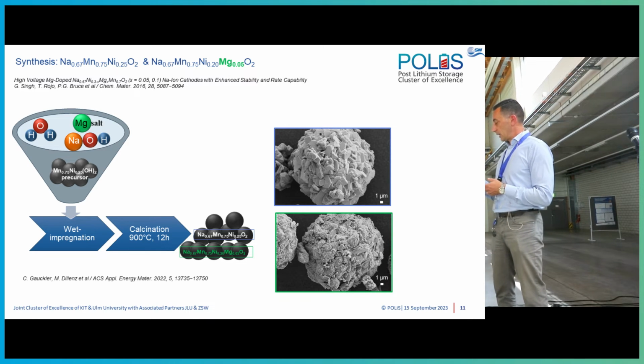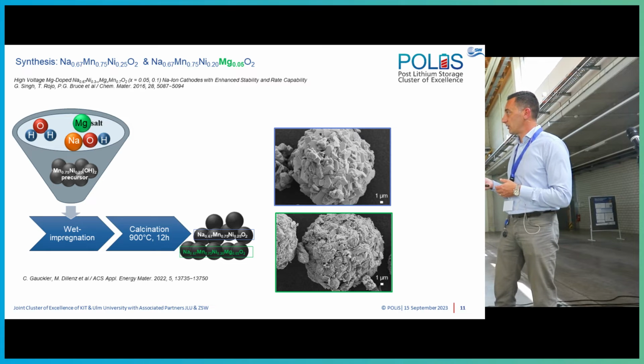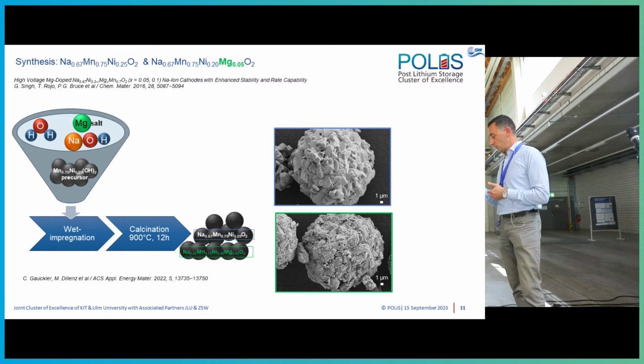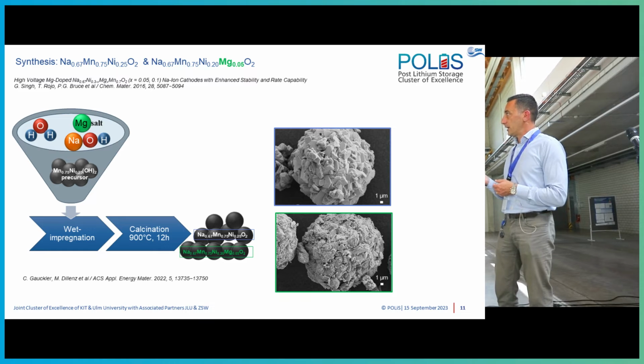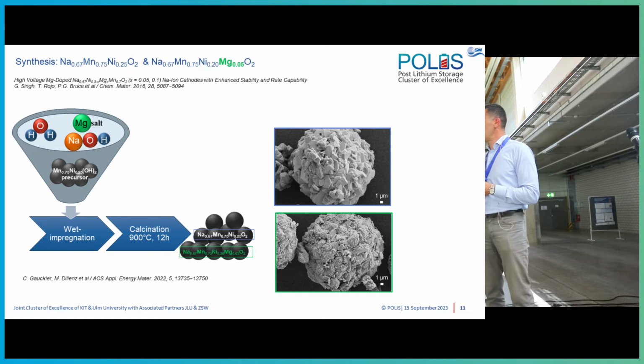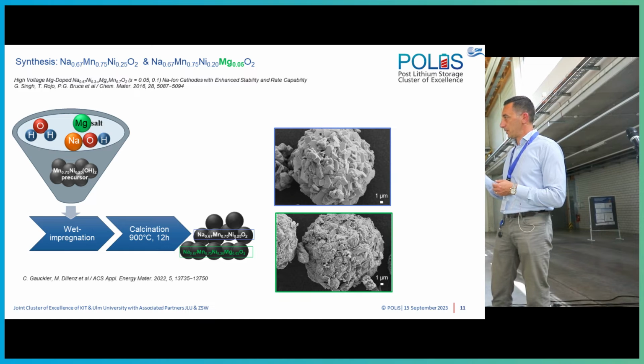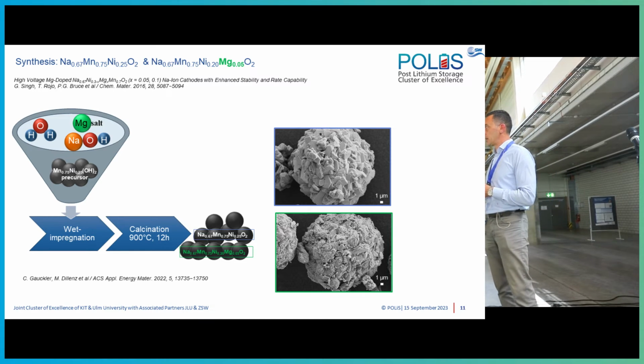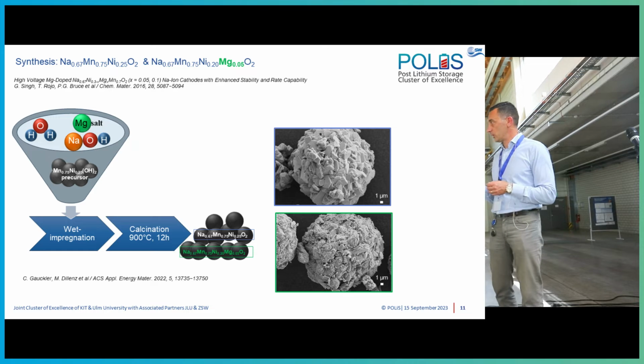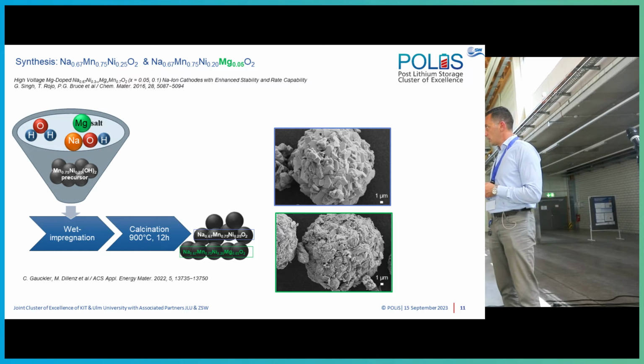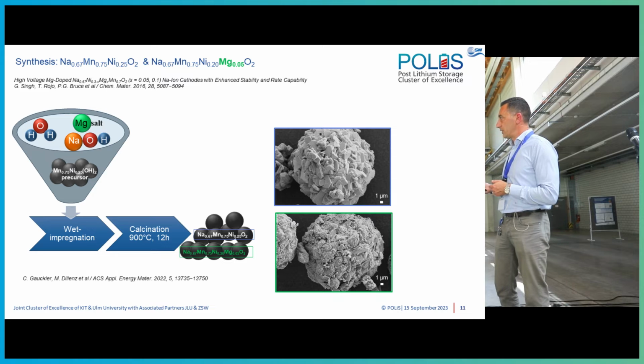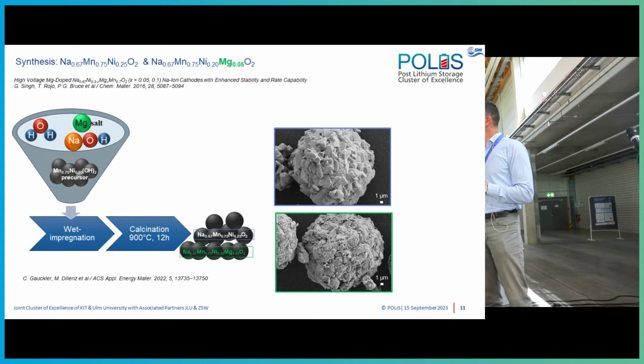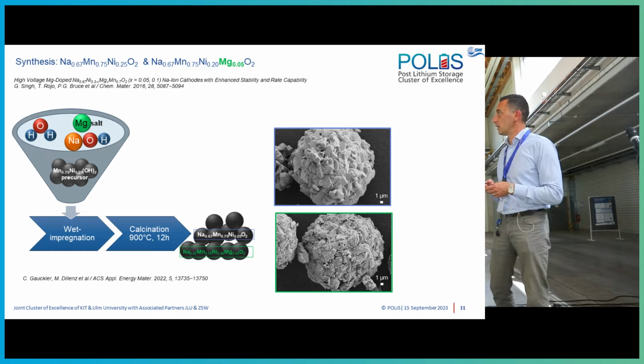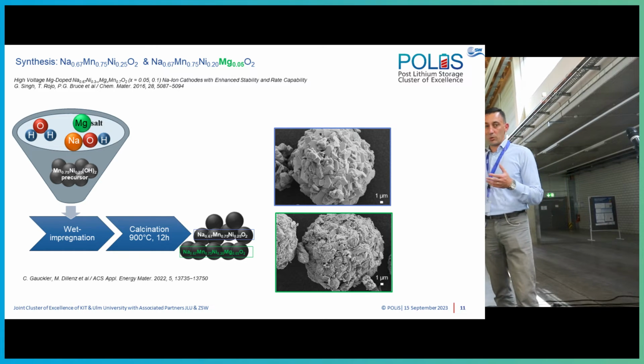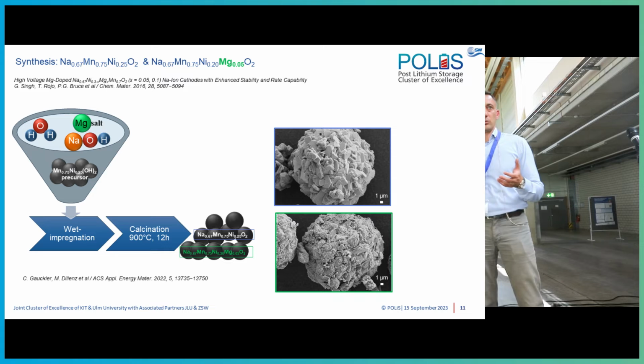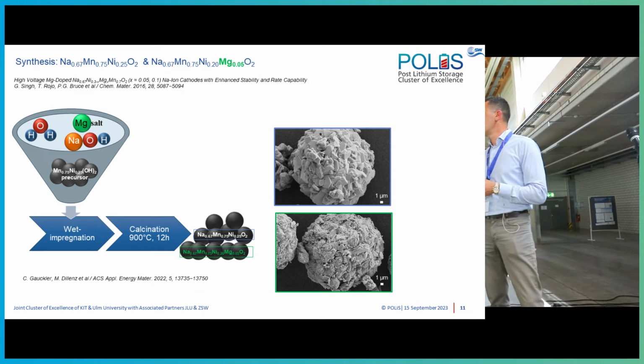So we started, as I mentioned, with the baseline material, 75-25. This is the ratio of nickel and manganese. And then we had a magnesium salt. We did the wet impregnation and then the calcination at 900 degrees C for 12 hours, and what we get is this. The surface looks a little bit different, but when we go into X-ray diffraction, what we see is that both materials retain the same structure, so it's a P2 structure.